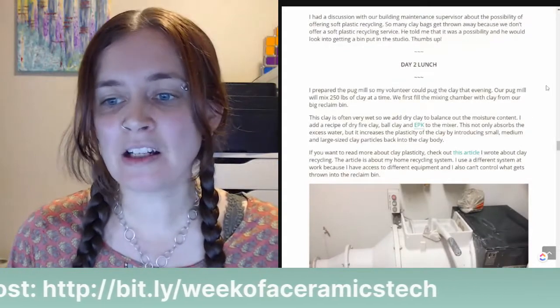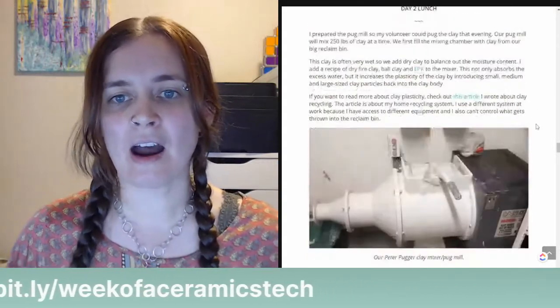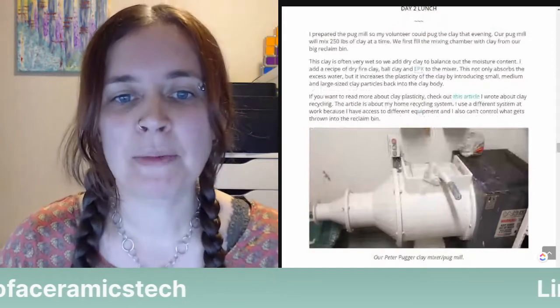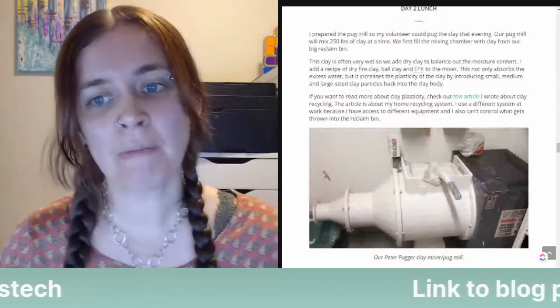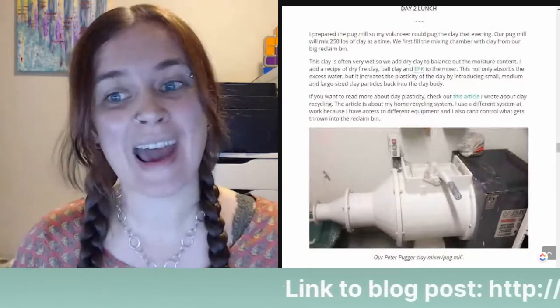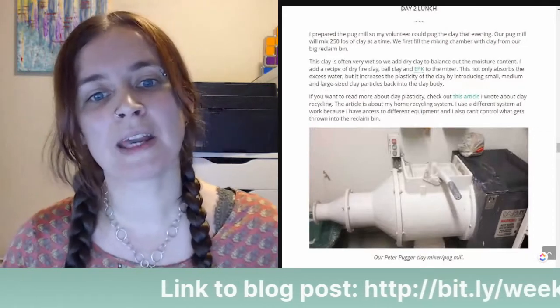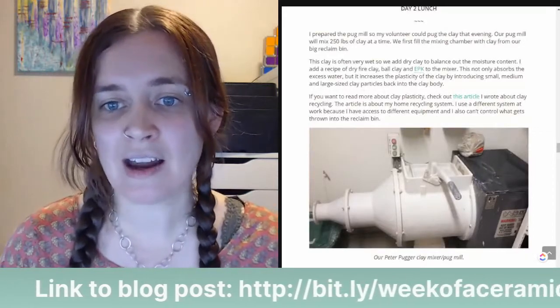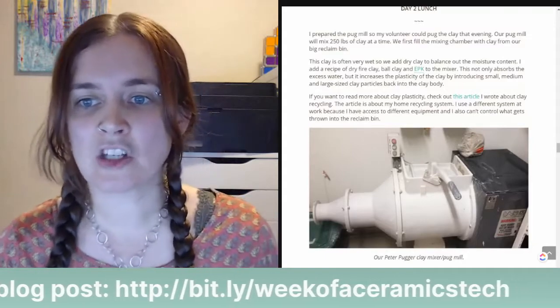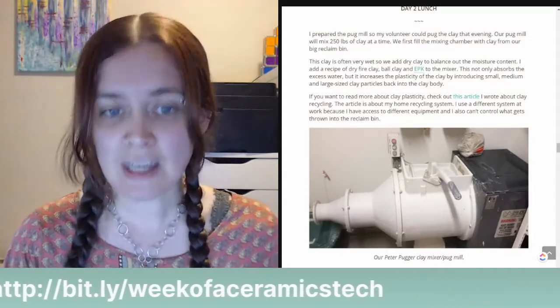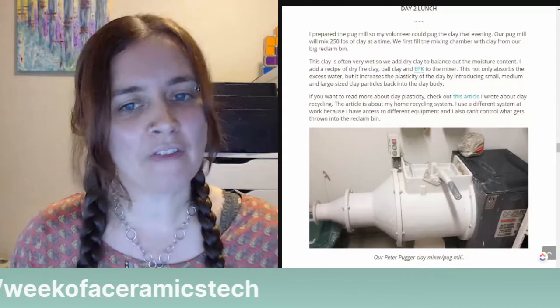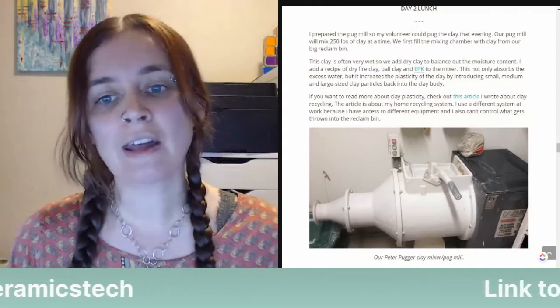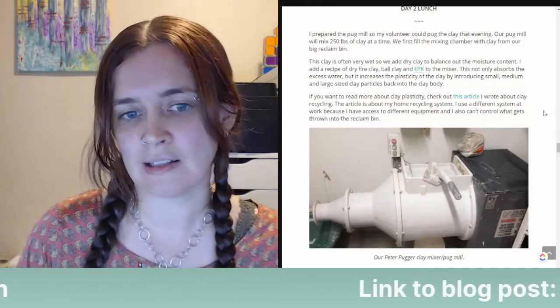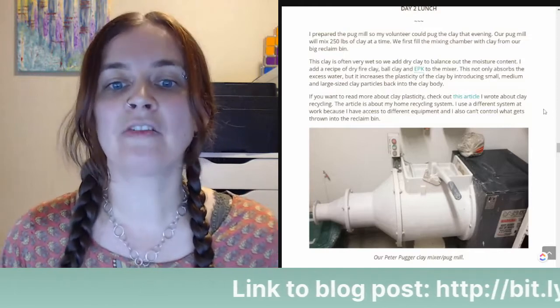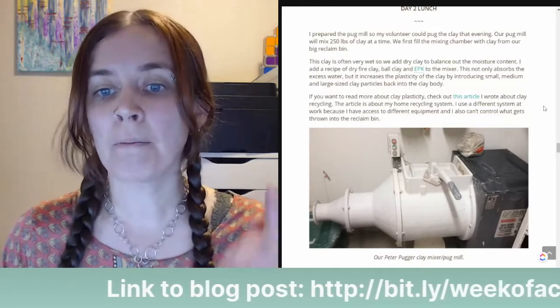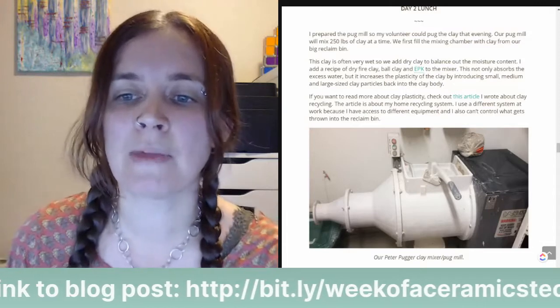Then I took my lunch break, and then Wednesday afternoon, I prepared the pug mill so my volunteer could pug the clay that evening. Our pug mill will mix 250 pounds of clay at a time. We first fill the mixing chamber with clay from our big reclaim bin. This clay is often very wet, so we add dry clay to balance out the moisture content. I add a recipe of dry fire clay, ball clay, and EPK to the mixer.